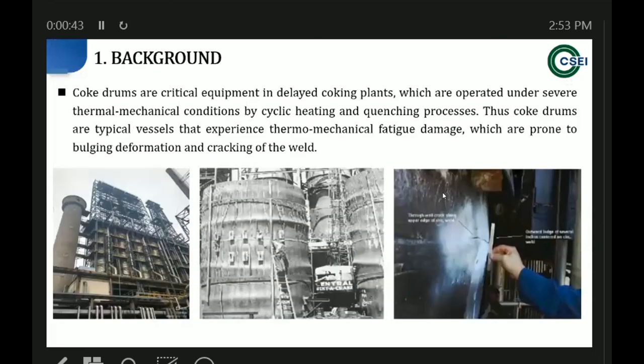The first part is the background. We know the drums are critical equipment in delayed coking plants, and they experience thermomechanical conditions from the cyclic heating and quenching process. So they also experience thermomechanical fatigue damage, and are very prone to bulging deformation and cracking at the weld. It's very common for this equipment.